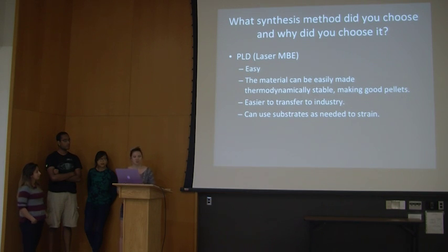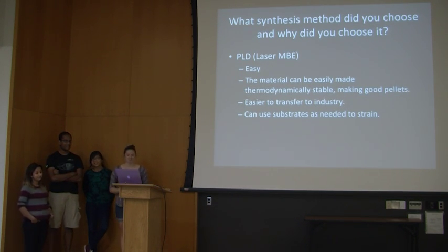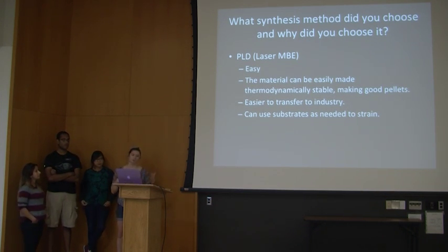So how pulsed laser deposition works is you basically make a pellet out of your target material. You could straight up mortar and pestle it, grind it all together and make a puck, and then you put it in there and shoot it with the laser, so then it comes out over here. Unfortunately, the person that knew the most about PLD is not here right now. So that's the method we went with, and the other reason we wanted to use a thin film approach is because you can use different substrates if you can get an epitaxial relationship and strain it a little bit, which can affect structures down the line. So that is why we chose PLD.